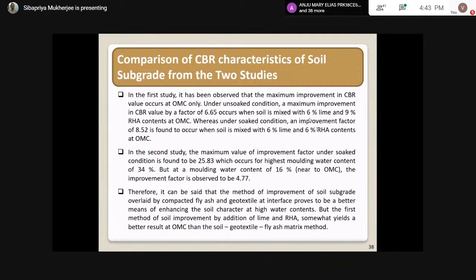So this is the comparison between the studies, which I have told you. It is given here in terms of improvement factor. We can see that the maximum improvement in CBR value is 6.65. It occurs with soil with 6% lime and 9% RHA at OMC. This is for unsoaked. For soaked condition, the improvement factor is 8.52, which occurs for 6% lime and 6% RHA content. And in the second study, the maximum value of improvement factor under soaked condition is found to be 25.83, which occurs for the highest molding water content of 34%, but at a molding water content of 16% near OMC, the improvement factor is not so high, it is 4.77.